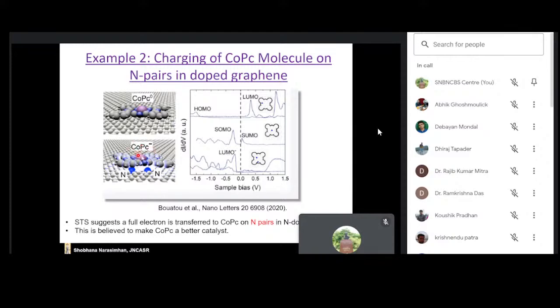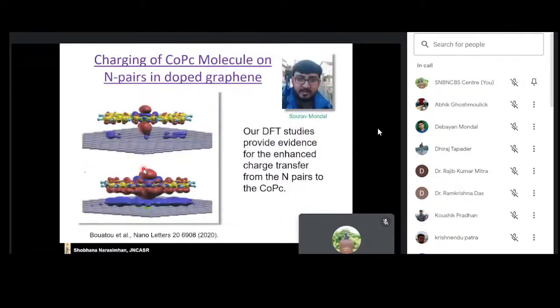And as a result, the oxidation state of the cobalt changes, and this makes it a better catalyst. And we can see that in DFT also. So here, in these kinds of plots, which are called charge transfer plots, red lobes show that electrons have been gained. Blue lobes show that electrons have been lost. Here it is over a single nitrogen dopant, and you see that a little bit of electrons are gained by the molecule. But if it's over a nitrogen pair, you see a lot more negative charge is gained. And this is what changes the oxidation state of the cobalt center and makes the system a better catalyst.